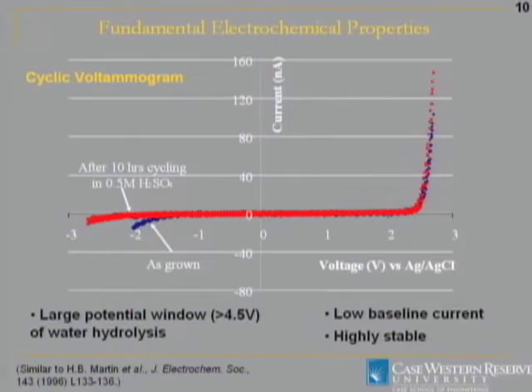So again, here's that voltammogram for diamond. What I wanted to point out is it does have a very large potential window. Platinum's window is only about 1.5 volts for comparison, and I'll show you that in a few minutes for the neural stimulation part. The low baseline current here is probably about 10 times lower than other metals and carbon-based electrodes, which should increase sensitivity. And this was a scan of 10 hours of cycling. It didn't really change anything on the electrode.